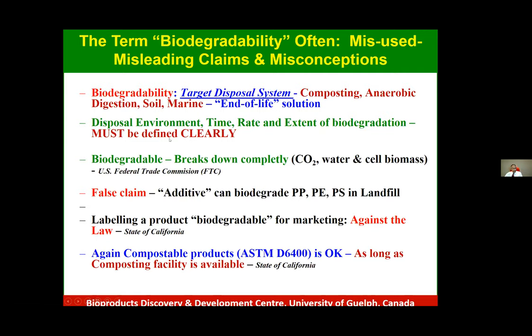So this must be clarified. Otherwise, only saying my product is biodegradable is a misconception and misleading to the public. Biodegradable should completely break down in the composting condition, as for example, into carbon dioxide, water, and cell biomass. False claim: people claim an additive can biodegrade polypropylene, polyethylene, polystyrene in landfill. That's completely wrong. Partial biodegradable doesn't make any sense. Breaking down is not biodegradable. Sometimes breakdown of plastics might create nanoplastic or microplastic. That's more dangerous than not biodegrading.